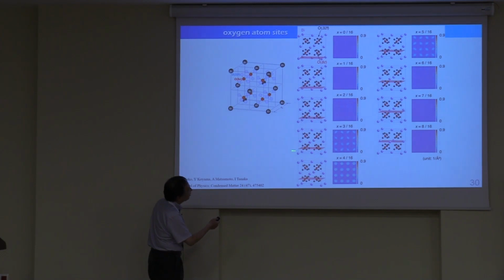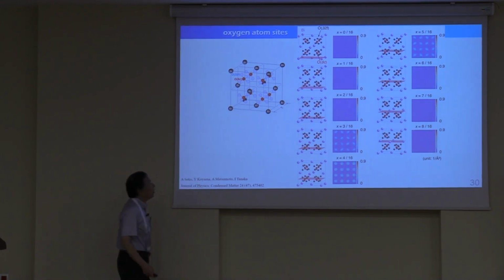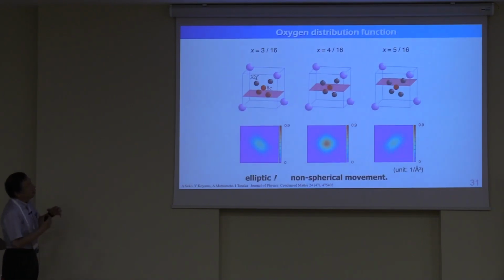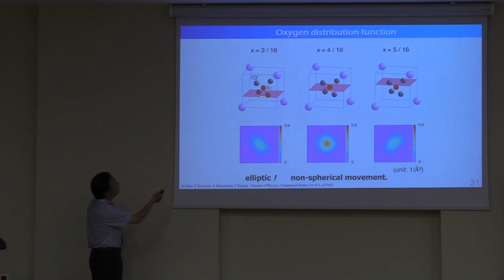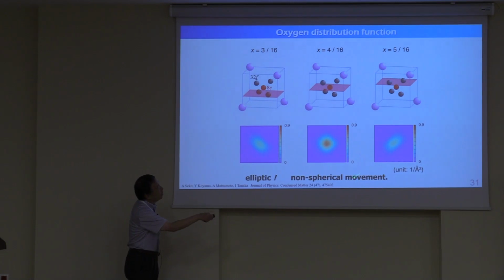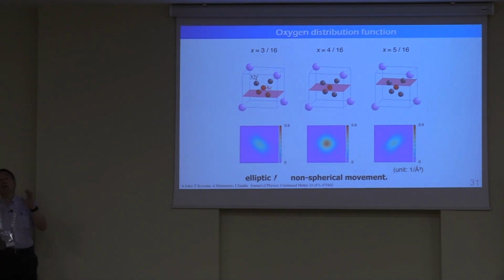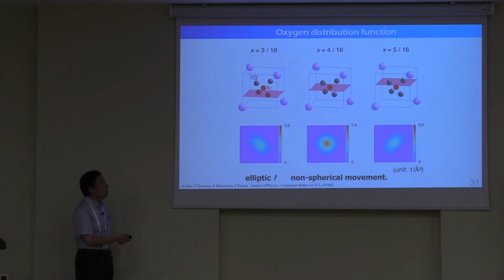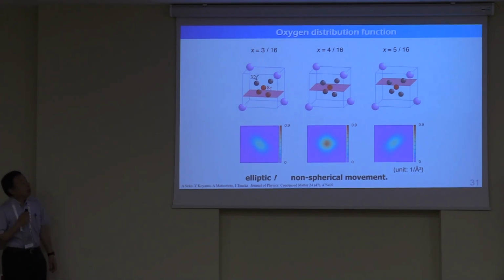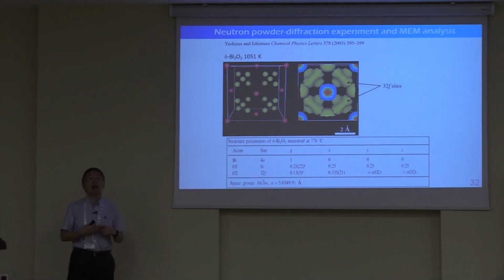If you cut this crystal at this 100 plane like this, you can find some of the trajectory of ions like that. And, well, this is so small, so let me expand that. At this height, the oxygen is moving toward that direction. And this side is almost spherical, and this side is going toward that direction. It means the atomic movements are not spherical, it's elliptic movement. So this is quite interesting, and also it was very well confirmed by experiment.